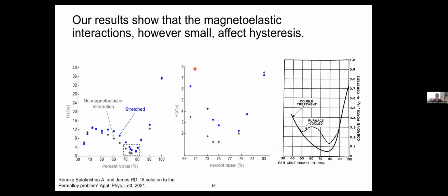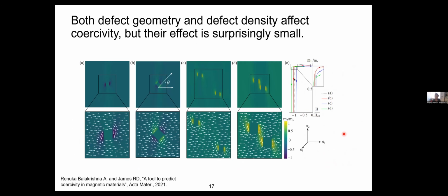And so what this calculation showed us is however small the magnetoelastic interactions are, they play a role in affecting magnetization reversal. And one explanation towards why there's a minimum coercivity at 78.5% is the delicate balance between these material constants that's giving us the minimum hysteresis width at this composition. And that makes us rethink as to what if we change the geometry of the defect? What if we introduce multiple defects? Is this calculation going to change?